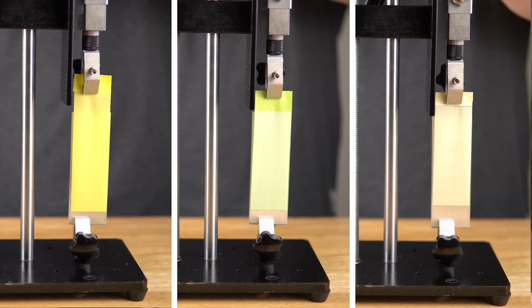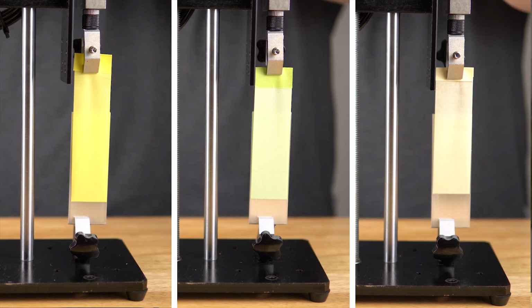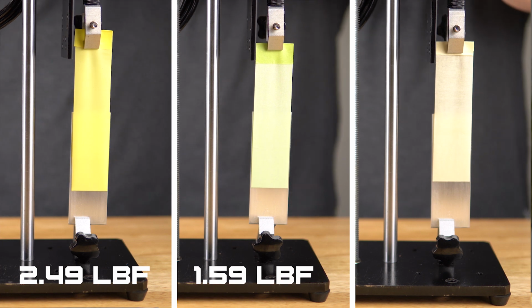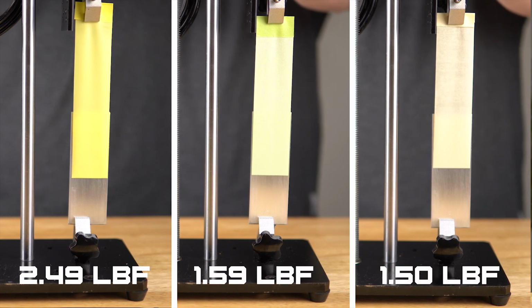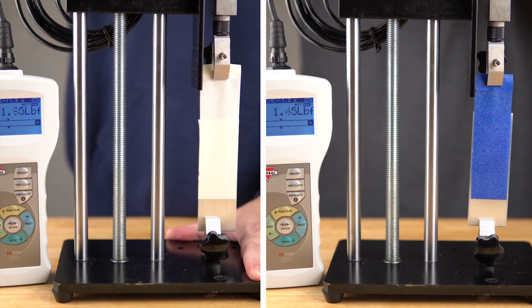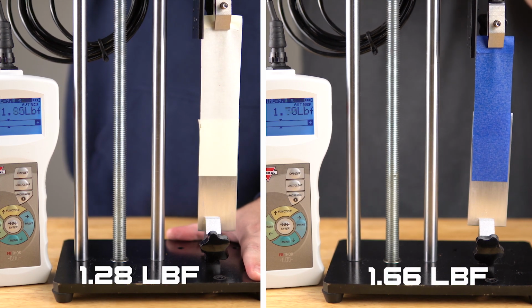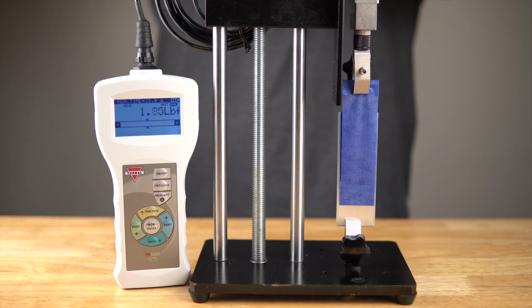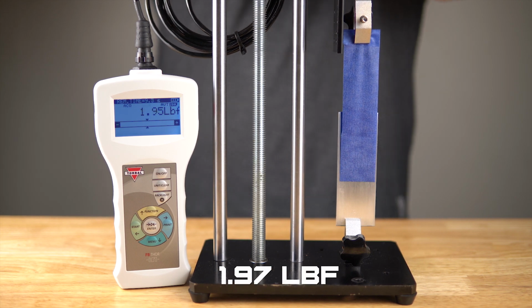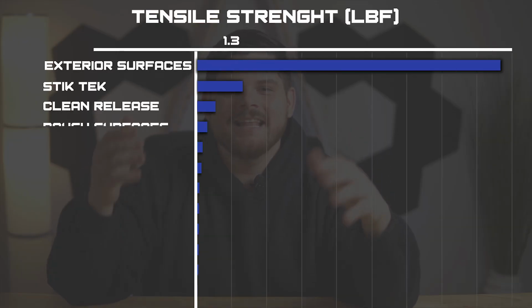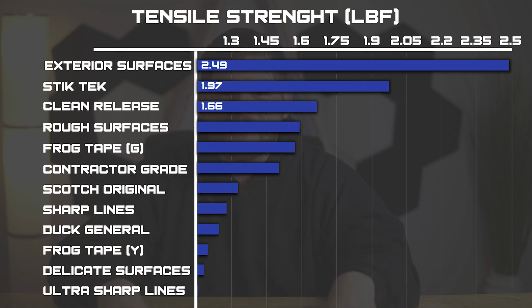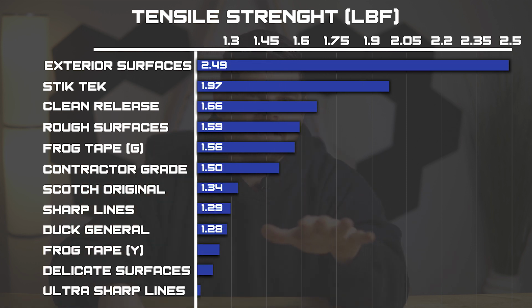Scotch Exterior, Rough, and Contractor grade tapes had a whopping 2.49, 1.59, and 1.50 pounds of force respectively. Duck Brand General Purpose and Clean Release came in at 1.28 and 1.66 respectively. Stick Tech had a very impressive 1.97 pounds of force of adhesive strength. As expected, the exterior tape had the strongest adhesive, while the 2 tapes made for delicate surfaces had a low adhesive strength. Once again, the Frog tape was in the middle of the pack, and Ultra Sharp Lines had a very low adhesive strength. Let's see if that comes into play on our next test.